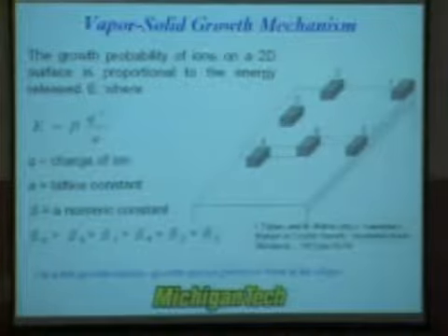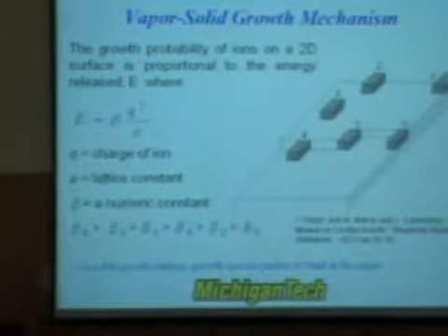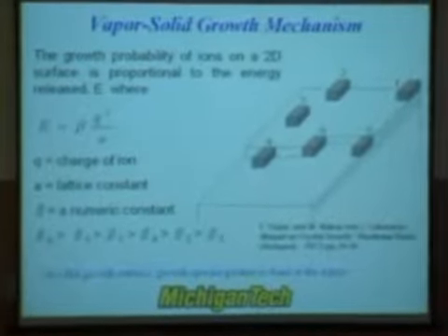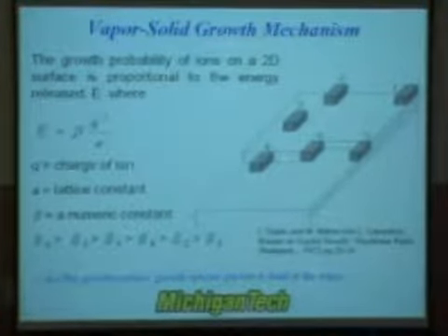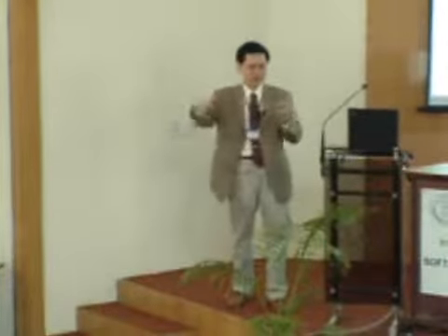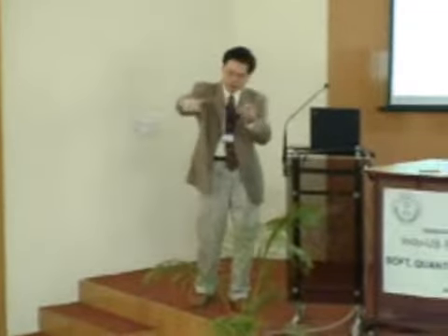And at the same time, if you look at the nucleation theory, you find that if you have a perfect atomic surface like this, you have only 1, 2, 3 possibilities for the atom to land on the surface. And you will see that number 1 and 2 are the preferential sites for growth. So, which means if you can cool down your growth conditions so that there is no growth at the center of the rod, they will confine the growth at the edges, just like what I show here, right?